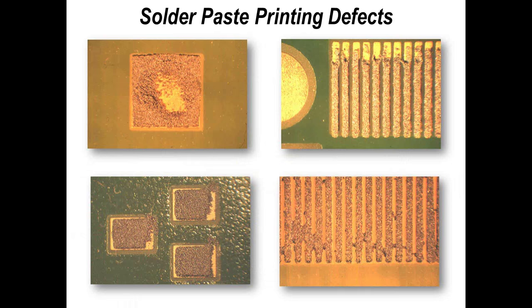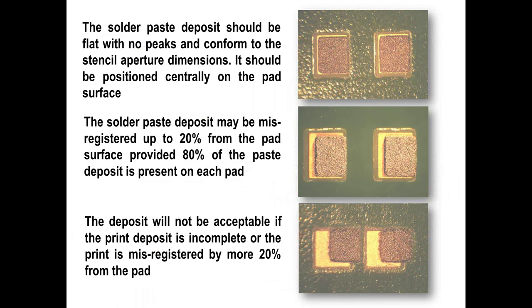On the bottom right, you can see what we refer to as wet shorts or wet paste shorts. And these are small particles of paste which are being forced between the apertures underneath the stencil and then being deposited on the next board. So this might be slow printing, it might be too high a pressure, it might be the stencil is not in contact with the pad sufficiently. A number of reasons can cause this particular type of defect.